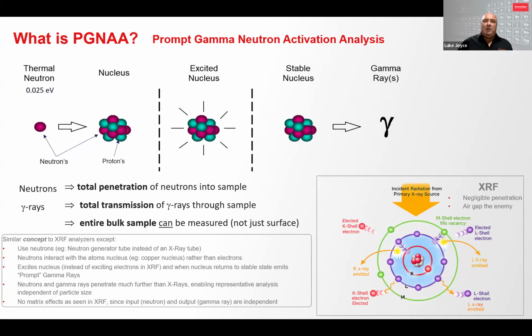Another key difference is that there are no matrix effects as seen in XRF, since in PGNAA the input, neutrons, and the output, gamma rays, are independent, whereas in XRF, an X-ray emitted from a heavier element, higher than calcium on the periodic table, can excite lighter elements lower on the periodic table before reaching the detector, which impacts the detected X-ray spectrum and often requires recalibration for changes in mineralogy. PGNAA doesn't suffer the same issue with changing mineralogy.